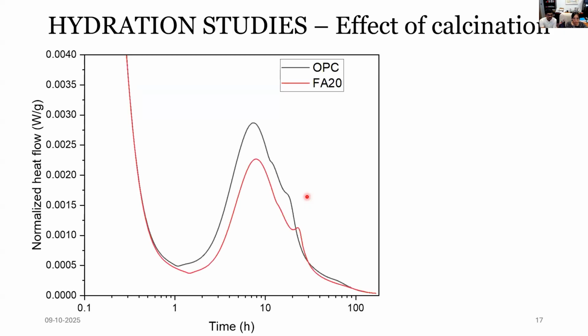So initially, coming to the hydration studies, in this slide we will see how calcination affects the heat release from the cement. In this slide, we can understand that with respect to OPC, when we replace cement with 20% fly ash, the reactivity is a bit slower, and it also dilutes the system, which leads to a reduction in the heat flow.